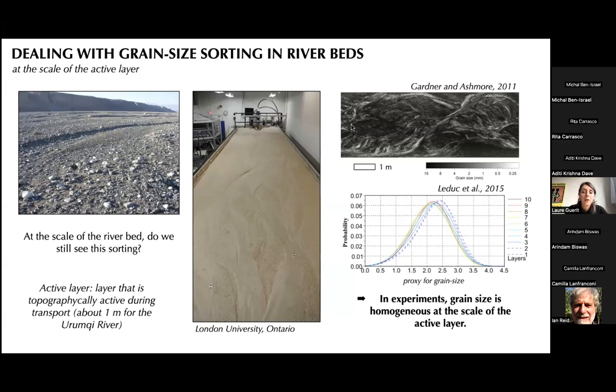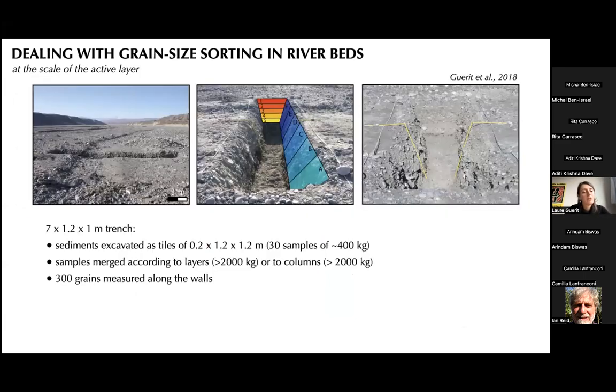Despite this very clear small-scale grain size sorting, do we have the same in this natural river? To answer this question, we go back to the Urumqi River and we dug a big trench across the riverbed. You can see it here. The trench is about 7 meters long, and we excavated sediment as 30 samples that are 1.2 meters by 1.2 meters and 20 centimeters thick, deep. In addition, we measured by Wolman counts the grain size distribution that was available on the wall of the trench.